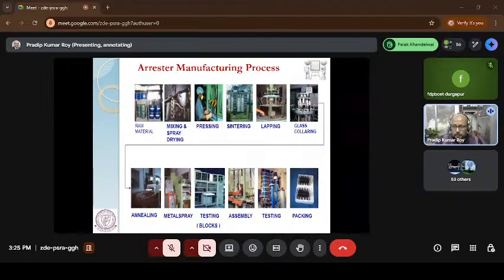After making that powder, the compaction is done, where these kinds of blocks that you have seen are fabricated. Then they are matured through the sintering process. Sintering is nothing but a heat treatment method to improve densification. Then they do the lapping. As I mentioned, both surfaces should be parallel, so they do the lapping with silicon carbide abrasive material. During lapping, the bottom plate moves in the clockwise direction and the top plate moves anti-clockwise. This way, they make the surface parallel.